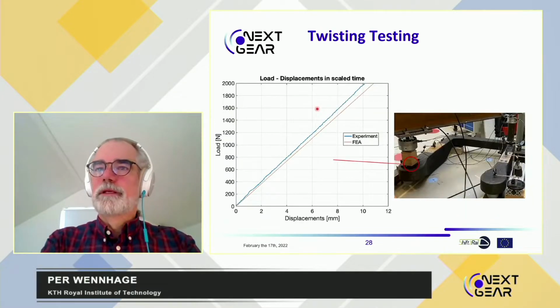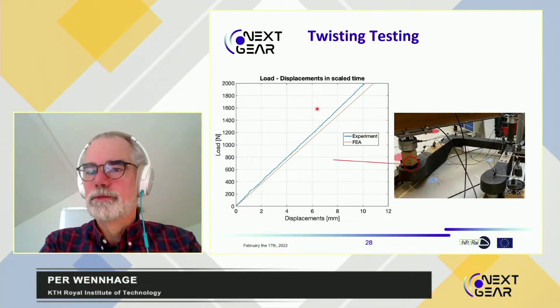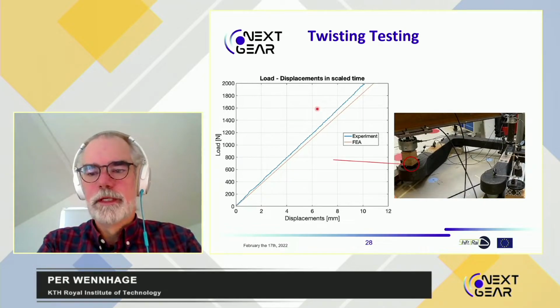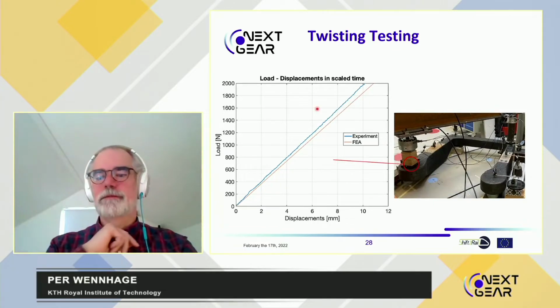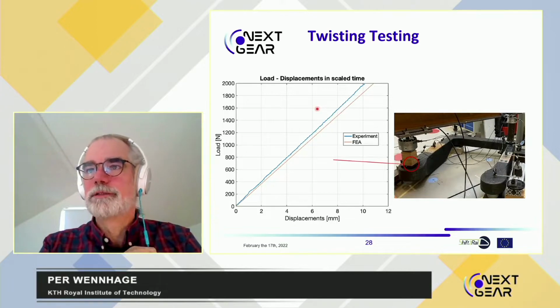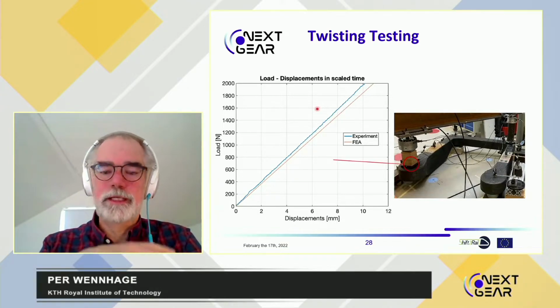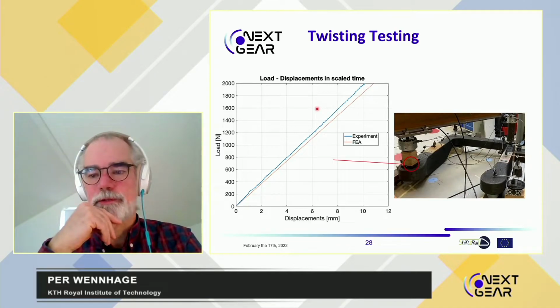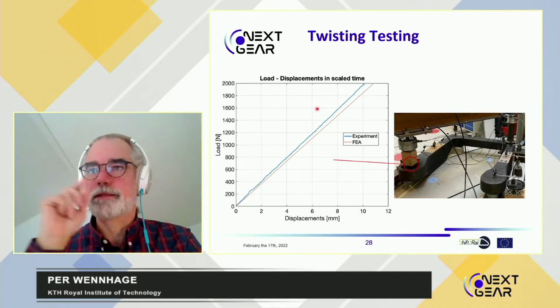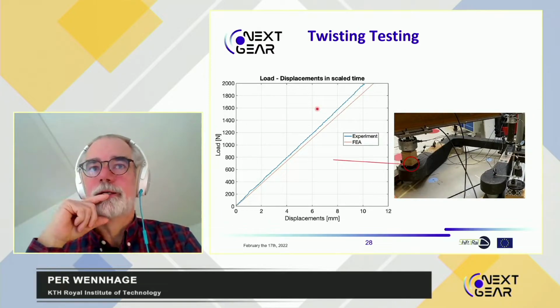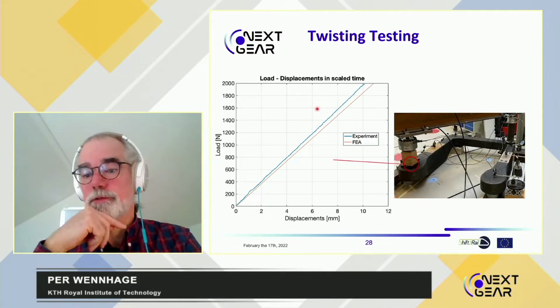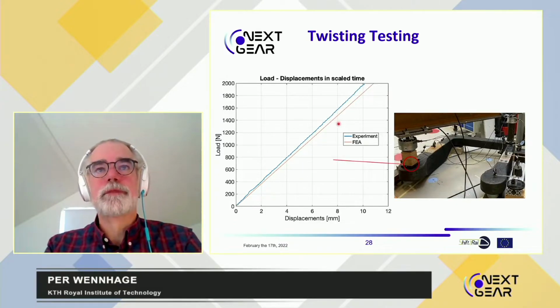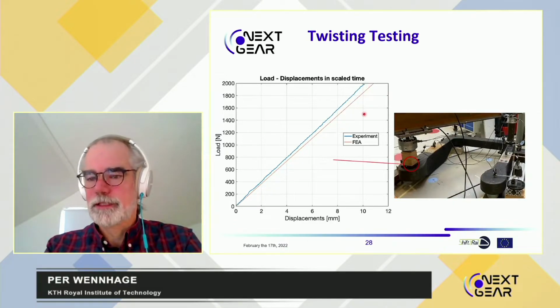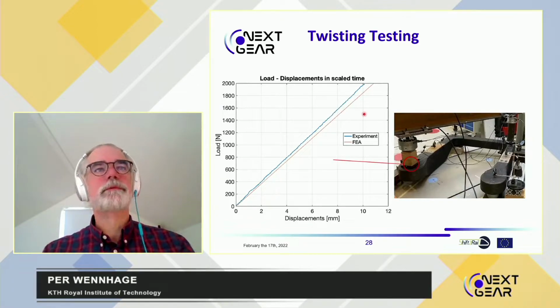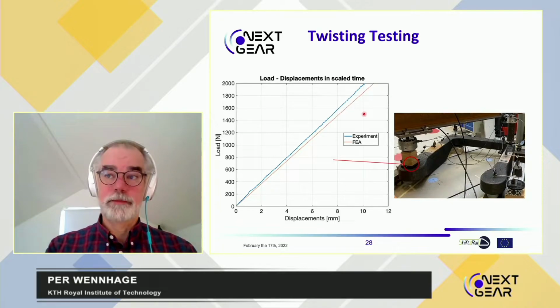Then we did a twisting test where we loaded 1/4 of the frame and the other ones were restrained. This is to simulate the action as an anti-roll bar to see if we got the stiffness right. And again, the finite element model that we used was a model of the actual test, the way it looked here. And as you can see, the results are also really encouraging. It may be a slightly bit stiffer than anticipated, but not way off. So we were very happy with this.